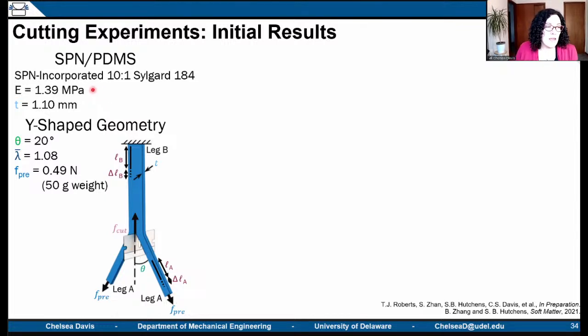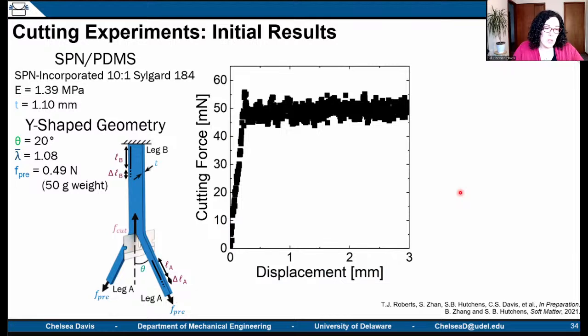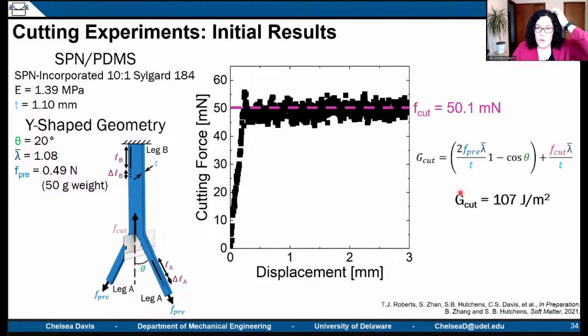And these are the parameters that we used for some of these experiments. So we're using the same exact mechanophore-functionalized silicone, still using a 0.6 weight percent loading of the mechanophore in our system. We get a modulus of roughly 1.4 megapascals for the Young's modulus. We're going to measure millimeter-thick samples with a half angle of 20 degrees, and you can see the other properties there. This is what one of these typical cutting curves looks like, where we can pull the F cut directly out of this. We know all our other parameters, so we get a cutting energy of approximately 107 joules per meter squared.